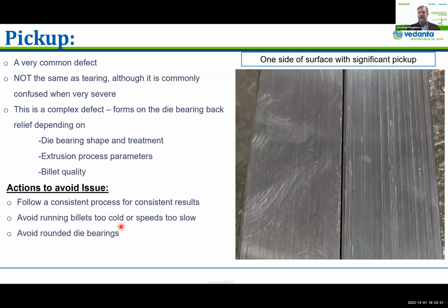And that's one of the reasons I wanted to make a distinction between pickup and tearing. Absolutely, with tearing, if you're overheating and having tearing, like we talked about on the previous slide, yes, that is a situation where you want to slow down. And then again, I mentioned die bearings, but particularly avoiding rounding the die bearings, and that could very easily happen in the polishing step. As most extruders polish manually, it's almost impossible to keep it perfectly flat. And if you have rounded bearings, you'll undoubtedly at some point run into surface issues.